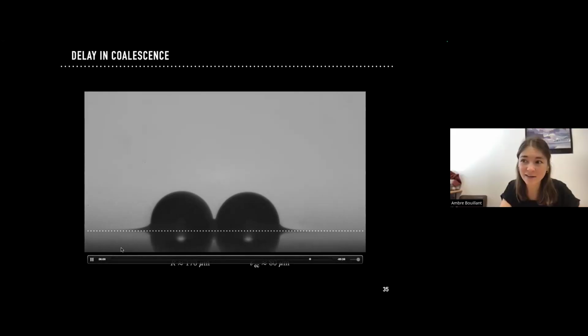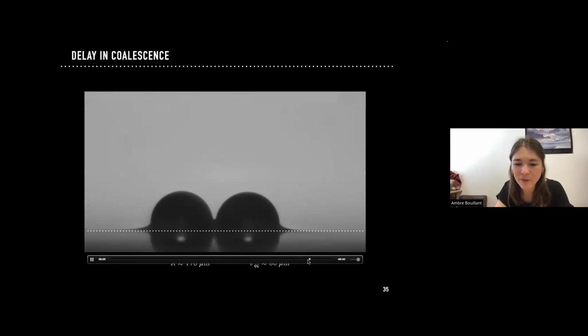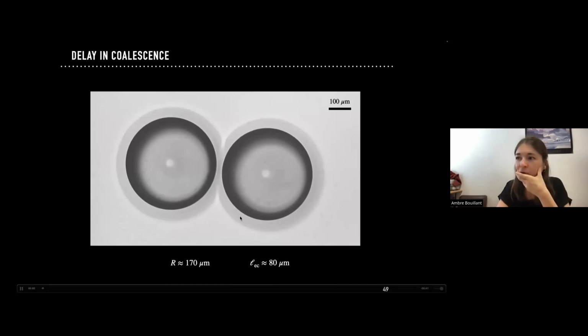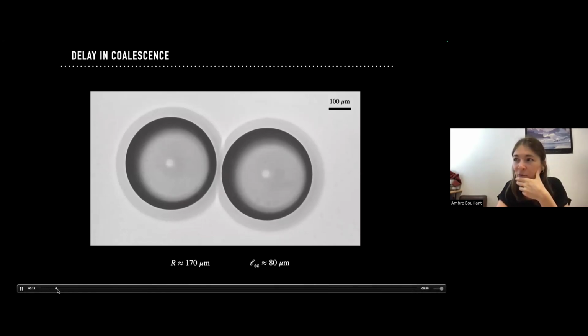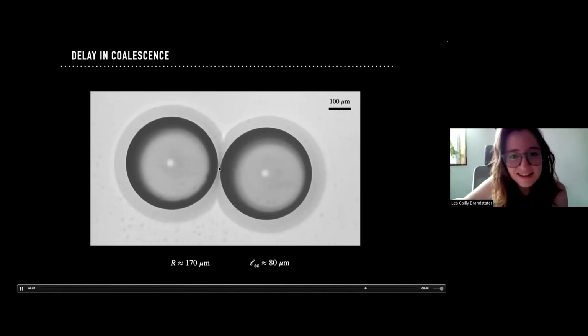And here I think it's a good question, because I have a few data for different gels. I also have a top view where you look at very tiny droplets, and you will see that these two droplets actually feel an attractive force from each other. I'm speeding up the movie because it's 5 minutes still. You see that they somehow deform and lose their circular shape, because this attractive force is exponentially decreasing with the spacing between the two objects. So it's very intense in the center and less pronounced on the edge, so you really deform your droplet because of that.